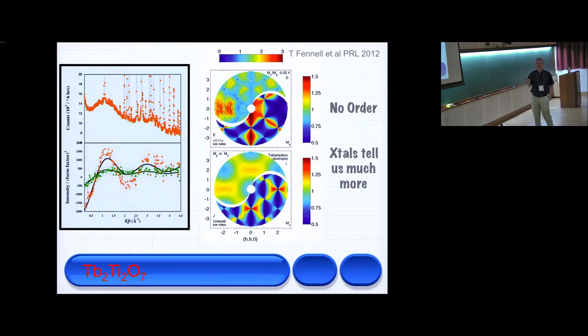What we normally do is take a high temperature data set where we believe it's a real paramagnet and just do a simple subtraction. So if you do a simple subtraction of this data set, you get these red dots here. So this is what we call the magnetic scattering from the sample in a very cheap and easy way. It's not the best way to do it, but it works quite well.